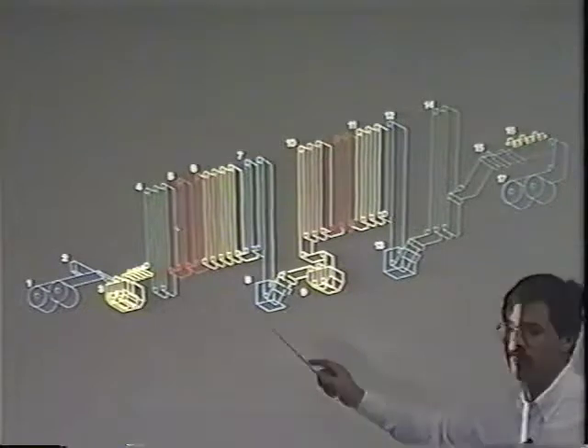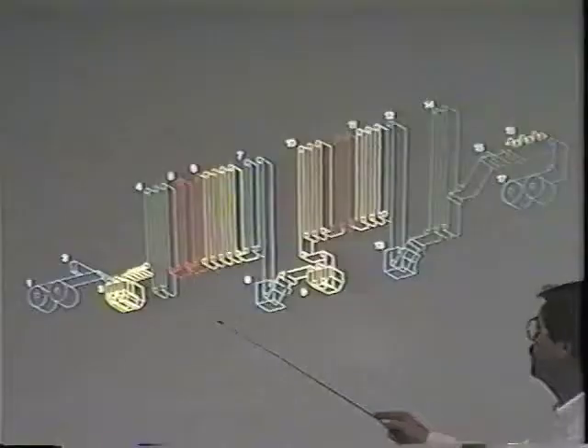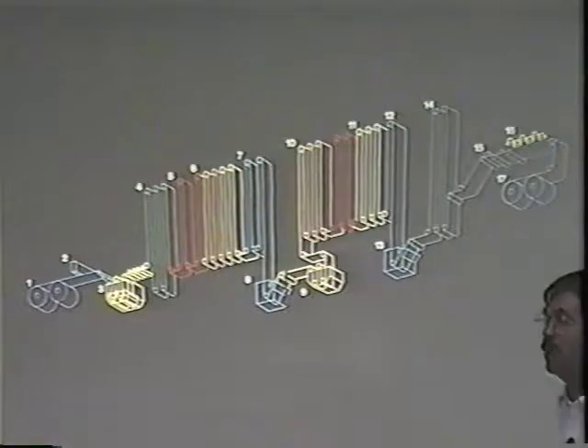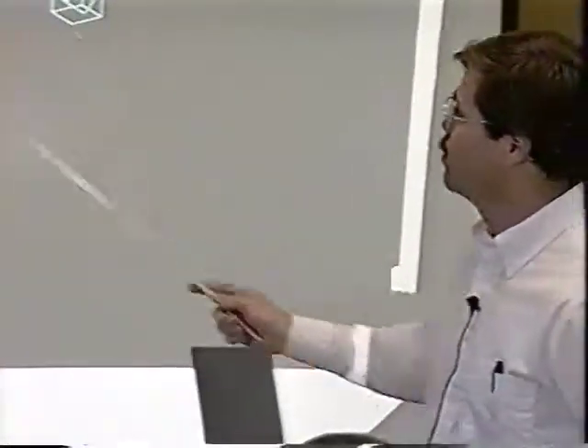First part of the continuous anneal process is a cleansing process. Remember I said that we tried to remove all of those rolling oils off the tandem mill? Well, we don't clean them all off. So the first part of the process here is to clean it, get the rest of those residuals off so that when you heat it up, you've got a clean strip. That's the first benefit of the continuous anneal technology. When you're batch annealing, you get a residue of the residual rolling solutions that are on the strip. When they're heated up, they create a carbonaceous type residue. You can wipe your hand on a batch anneal coil and it'll be kind of darkish, smutty. Since we're cleaning this before we anneal it, we don't have that smut issue.